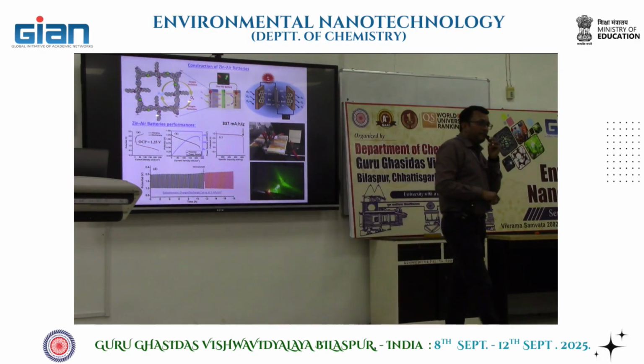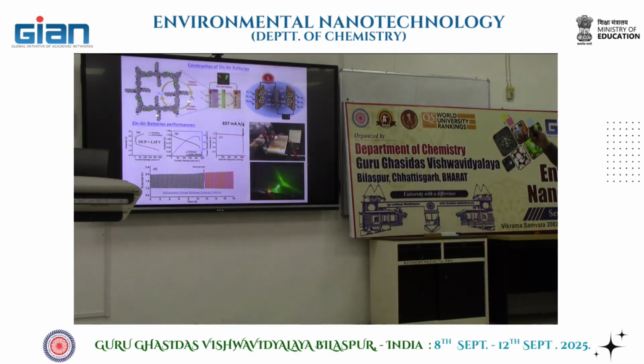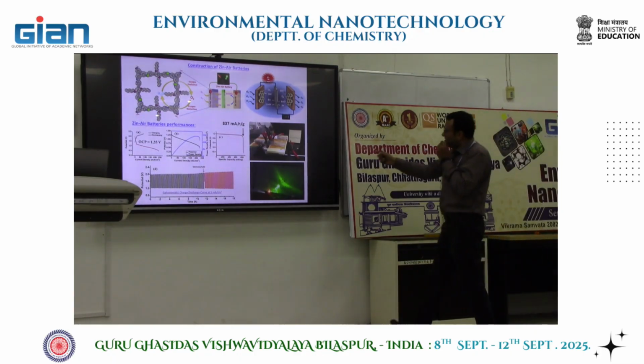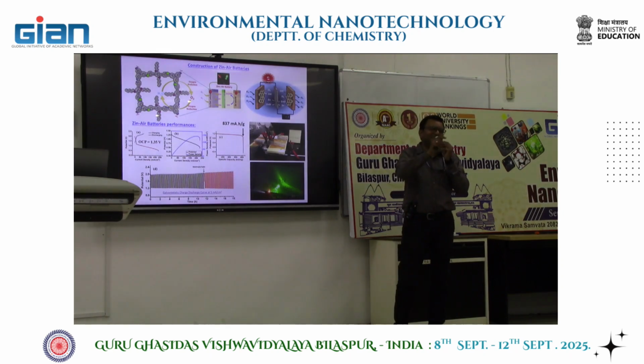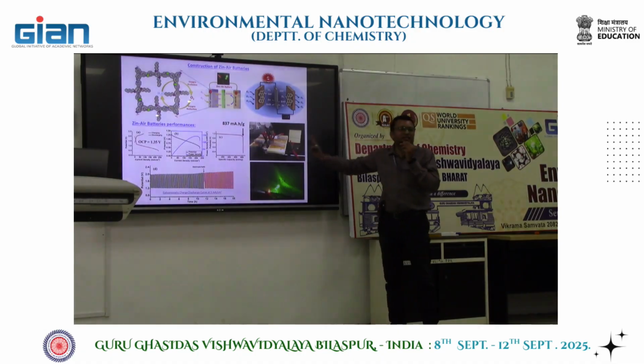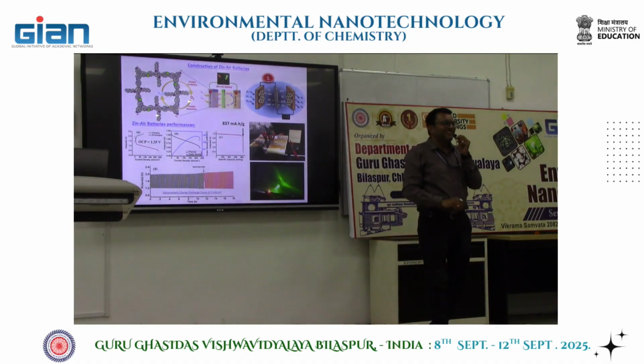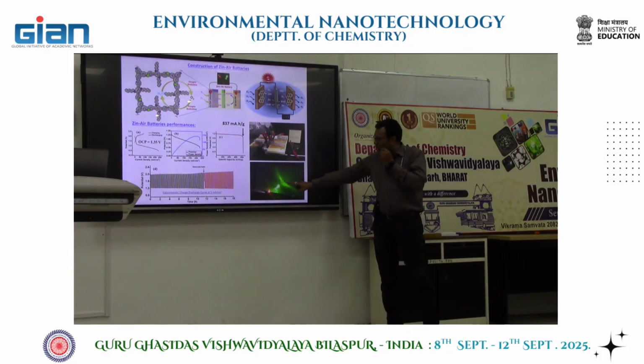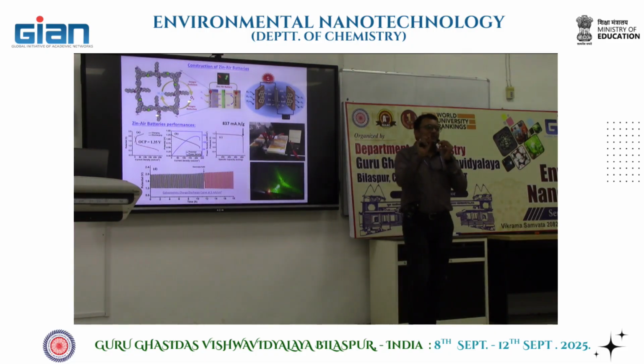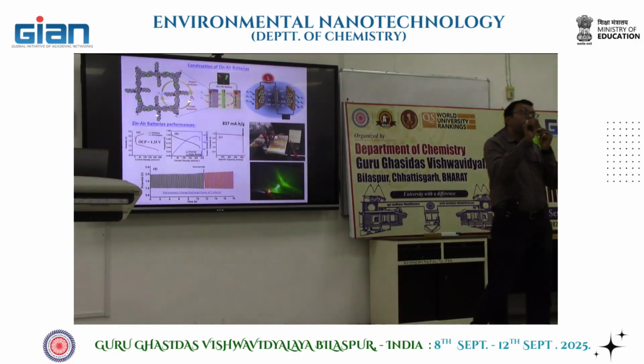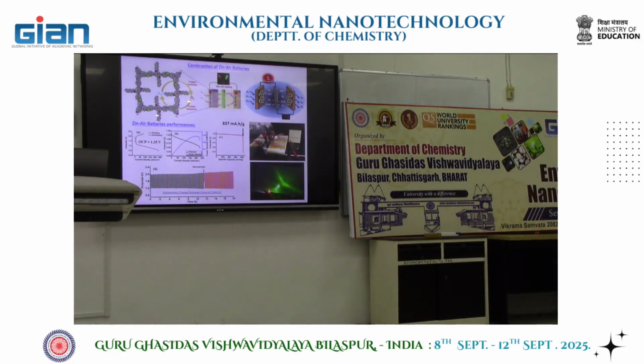For illustrating the practical application, we constructed this battery with 3 or 4 milligram of the product, with all the jugaad technology, and we found that two small LEDs were able to light for 48 hours without further charging. And of course, it gets discharged after 48 hours. You leave it for a few hours, you again start, it will again light.